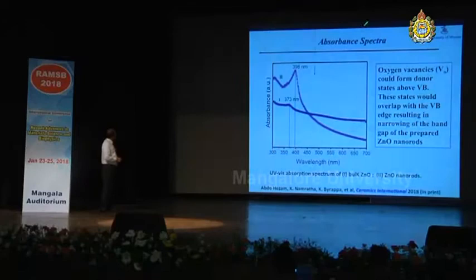Well, here we have studied the absorbance spectra, and oxygen vacancies could form donor states above the valence band, and these states would overlap with the valence band edge, resulting in narrowing of the band gap of the prepared zinc oxide nano rods that I showed in one of the earlier slides for zinc oxide prepared with some surfactant.